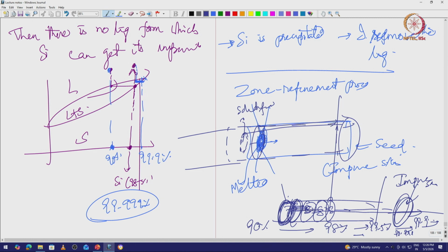If you understand isomorphous phase diagrams, it is easy to understand the zone refinement technique, right. You understand the phase diagrams and you have to actually construct this in your favor, right. So, if I am not removing the liquid, if I am just heating and cooling there itself, if I am not doing this physical motion of removing the ingot or removing the bar from wherever I am heating it, then I am not removing liquid from the solid, right. So, then I am still at liquid-solid equilibrium. So, I can heat it and cool it, but nothing will happen at that region, right. I have to heat it, remove it, right.